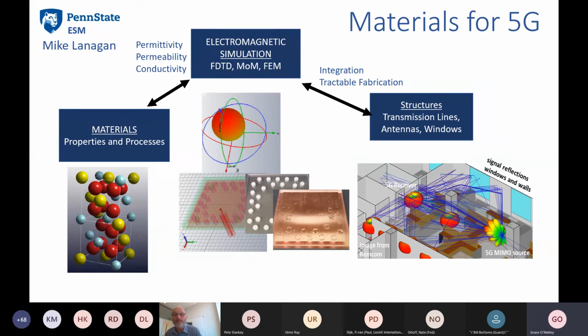Are there any approaches to increasing Q with implementing air voids? Yeah, that's a really good way to do it. Vacuum has a very low loss, and so adding porosity accomplishes two things. One is it lowers your permittivity, and two, potentially it could lower your loss. I think the one challenge, at least in the materials that I've dealt with, is that as you increase porosity, a lot of times those surfaces aren't super pure and maybe they'll pick up a little water, that sort of thing. So it is good to increase the porosity as long as you can control the surface and minimize any adsorbed species, because that becomes really important for loss.